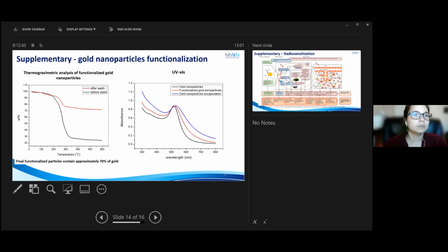Yeah, the particles are in organic solvent because they're functionalized with a hydrophobic polymer. Since PCL is hydrophobic, I can't change to water, otherwise they're just going to aggregate and precipitate. So that's why I'm trying to encapsulate them. There are not many studies doing hydrophobic gold because of that issue, because it's a very hard thing to do, especially at the concentration that you need. So unfortunately, they are in an organic solvent. I need to encapsulate in water and then remove the organic solvent by dialysis.